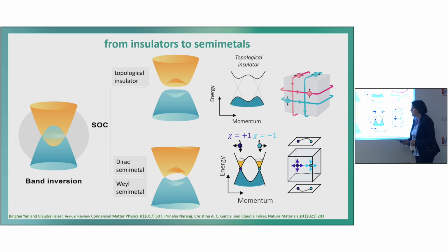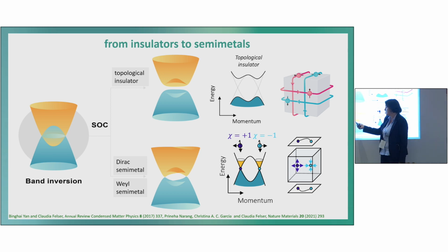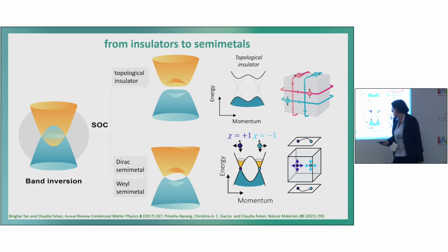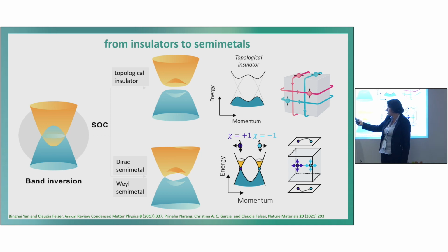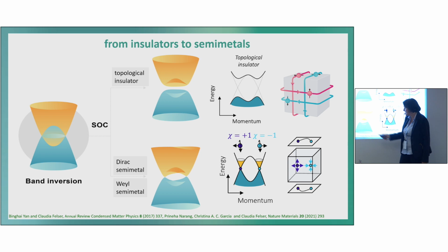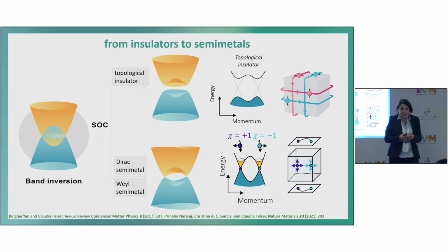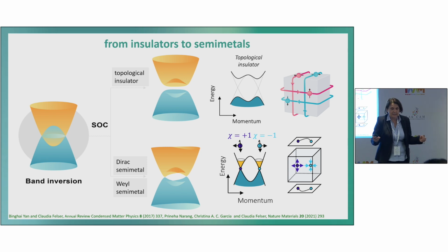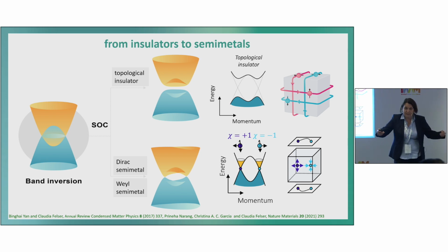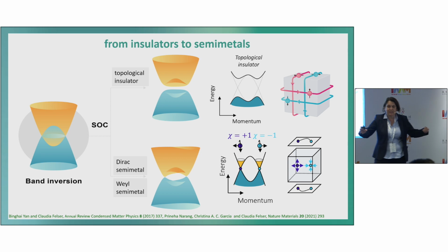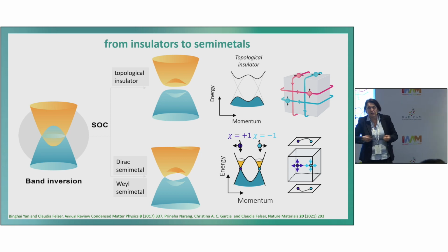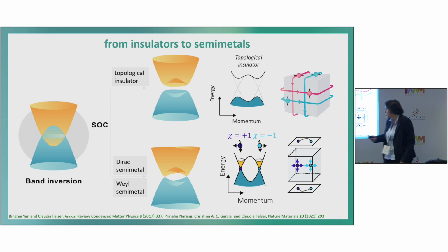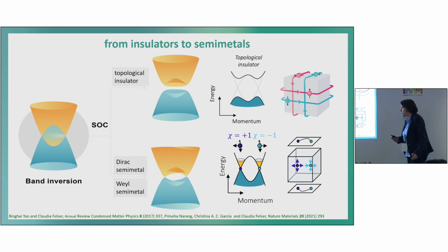The Dirac semimetal is when these degeneracy points are at high symmetry points, which means the materials are very often centrosymmetric, and in Weyl semimetals, these degenerate points are at low symmetry points. So we can transform even a Dirac semimetal into a Weyl semimetal by applying strain, by reducing the symmetry, making a centrosymmetric crystal non-centrosymmetric, or by applying a magnetic field or something else.